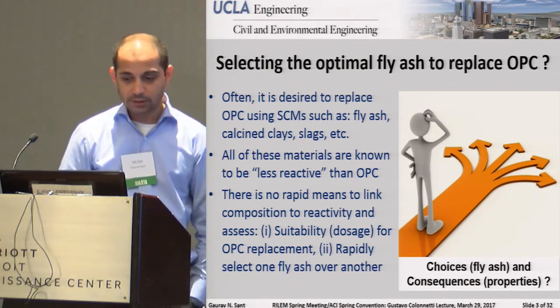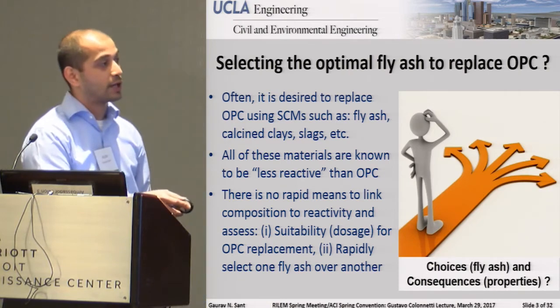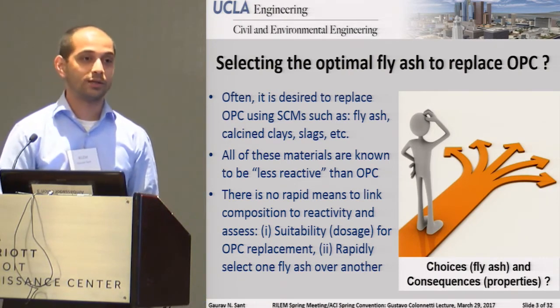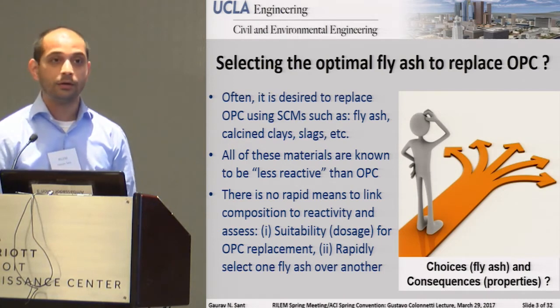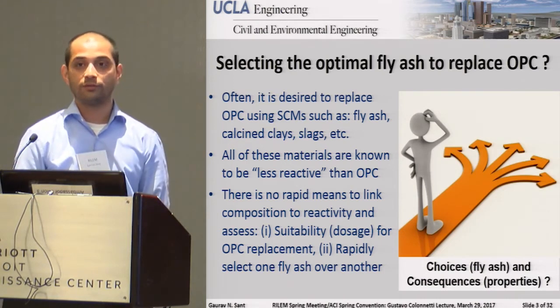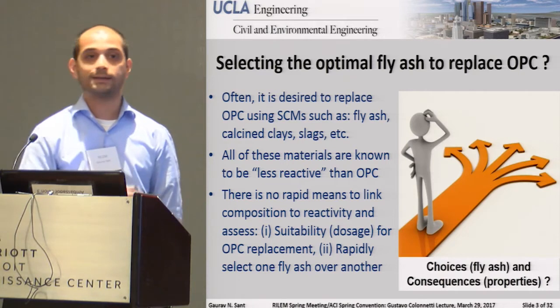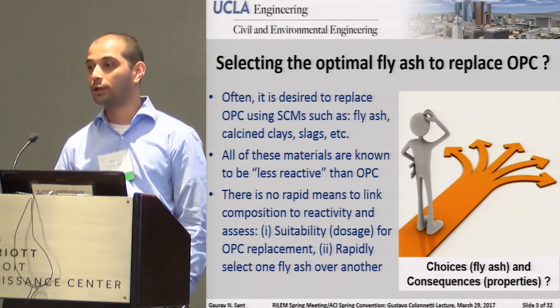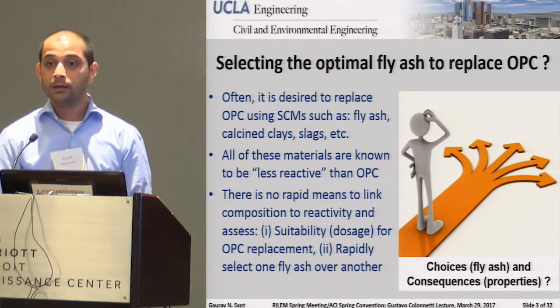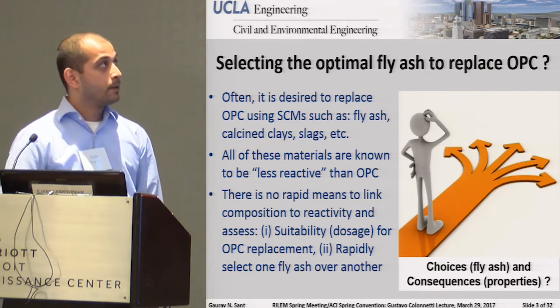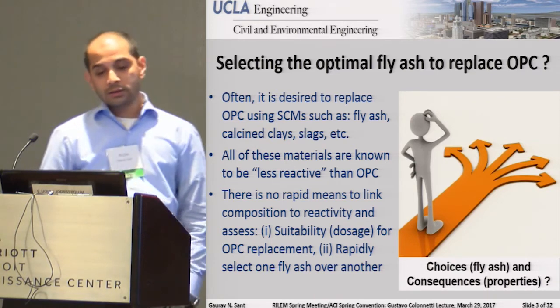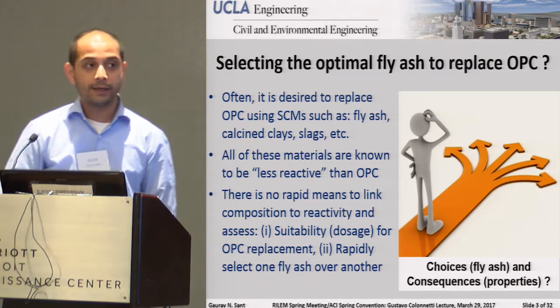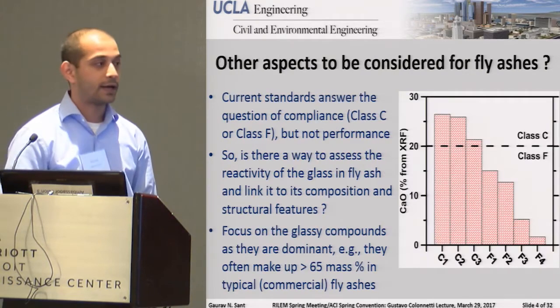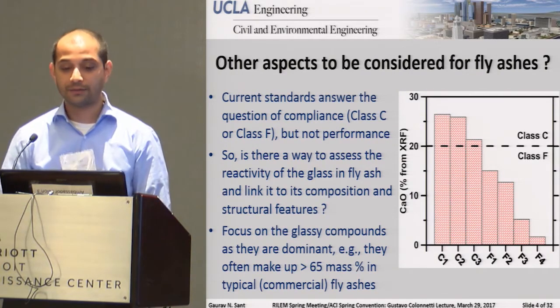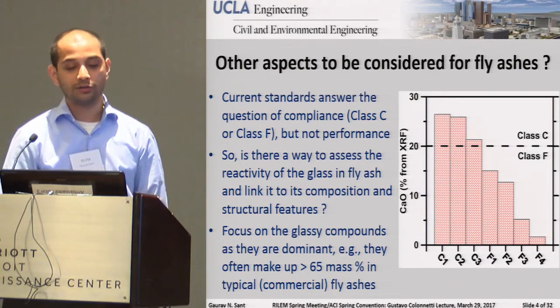Now, of course, this is important because when you select a fly ash, you've got to deal with the consequences, the properties that follow. So very often, you can hear the story about, well, we used a fly ash to replace Portland cement, we had an extended setting time, we didn't get the strength that we wanted at 28 or 56 days. These are important questions to be thinking of. Now, while current standards do look at the question of compliance, for example, whether fly ash meets a Class C designation or a Class F designation, they do not answer the question of performance.